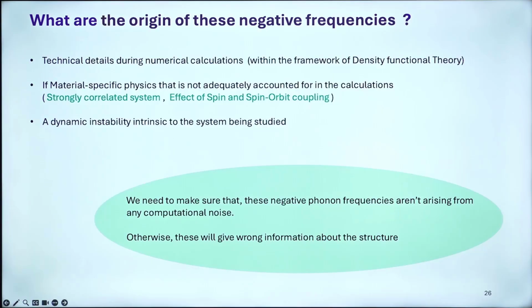So now, what are the origins of the negative phonon frequencies? Of course, one has to be very careful with the numerical calculation because we are working with density functional theory. If the material is strongly correlated, especially when you are dealing with rare earth or actinide systems where the spin orbit coupling matters, and transition metals also have considerable spin orbit coupling, then this will be very sensitive to it. There could also be a dynamic instability intrinsic to the system being studied, which could be related to the synthesis point of view also.